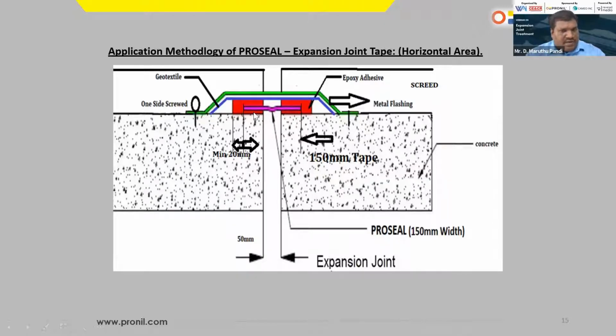All surface preparation, removing the dust and laitance, everything is very mandatory for waterproofing applicators. I'm just explaining how to fix the expansion joint tape on the substrate. So 4 mm of epoxy adhesive is mandatory to fix the TPE tape, with a minimum of 20 mm from the end of the tape to the concrete substrate, and from the end of the tape inside the tape. The first layer of epoxy adhesive should be 4 mm, and again a second layer of 4 mm should be applied. So it will easily catch hold of the tape on the substrate.